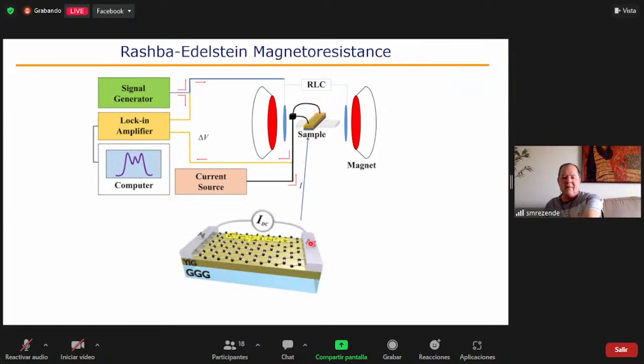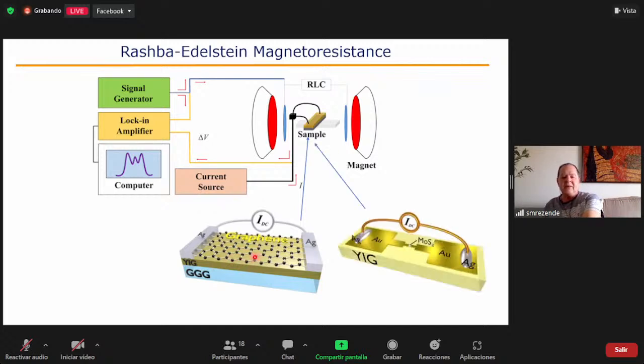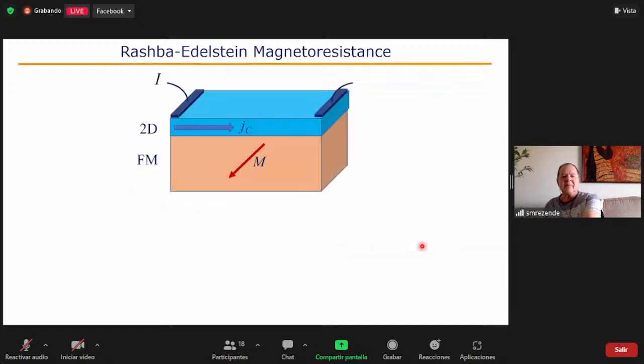For instance, we apply a current in the same device that I showed before, graphene on YIG, and we vary the magnetic field. We also did this in molybdenum sulfide, and we observed a very interesting effect. Let's say that we apply a current here. This produces a two-dimensional surface charge current in the 2D material. And this layer is in contact with the ferromagnetic material.